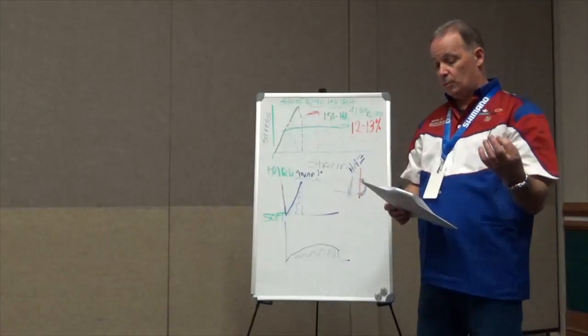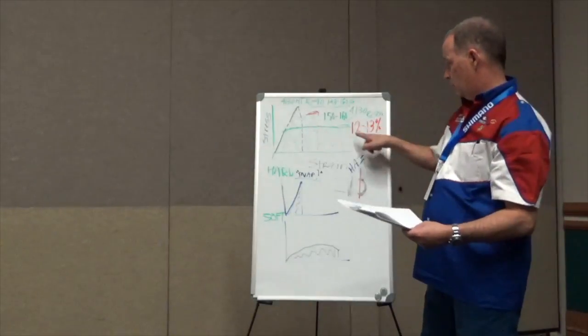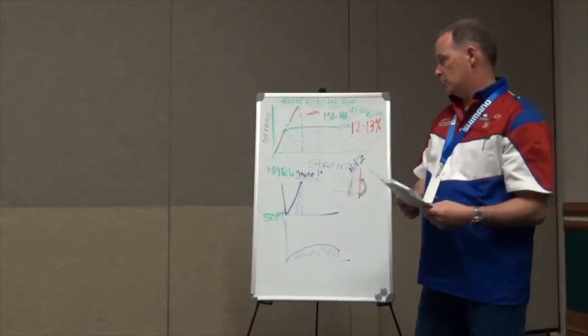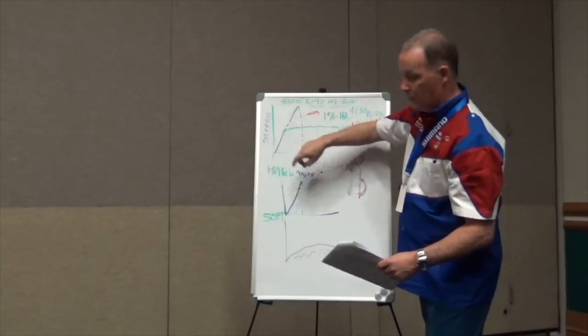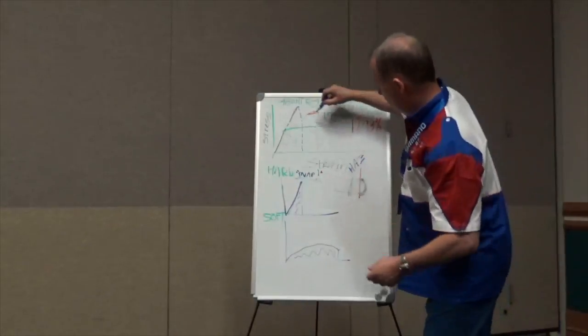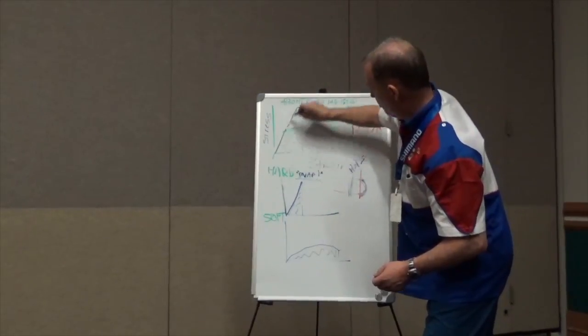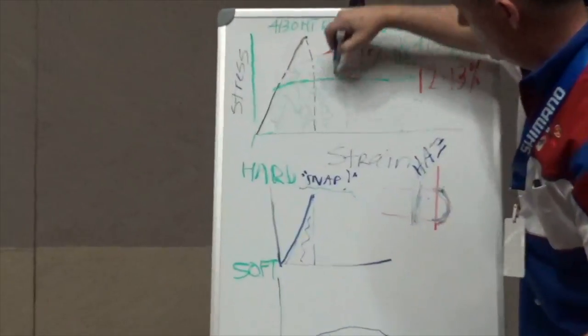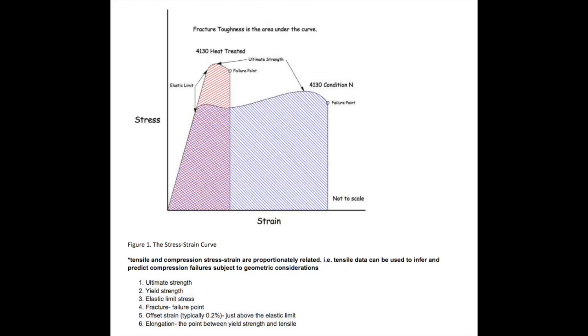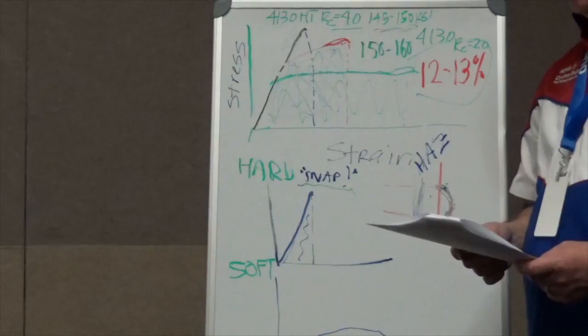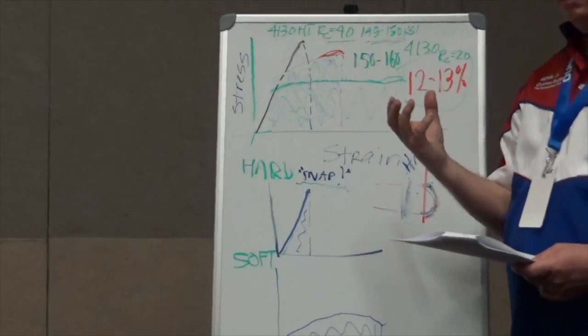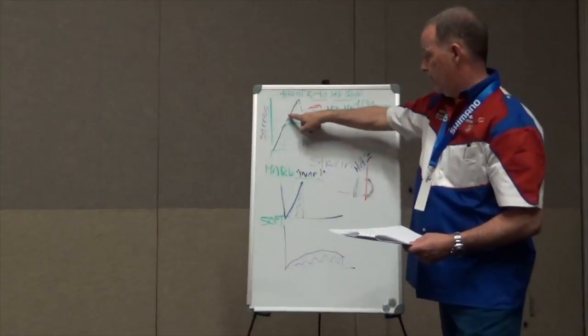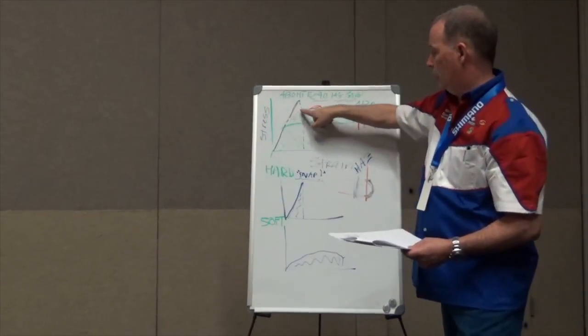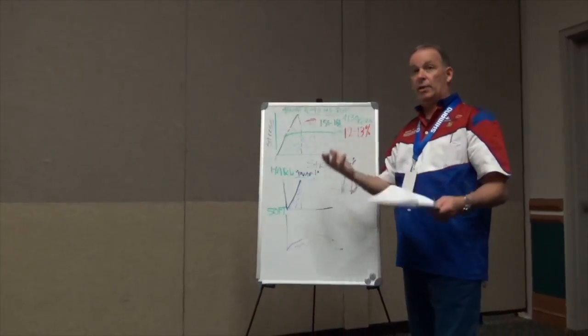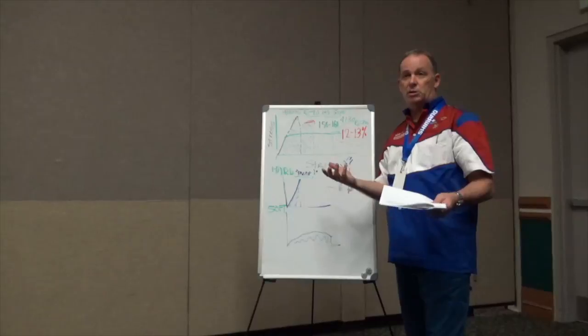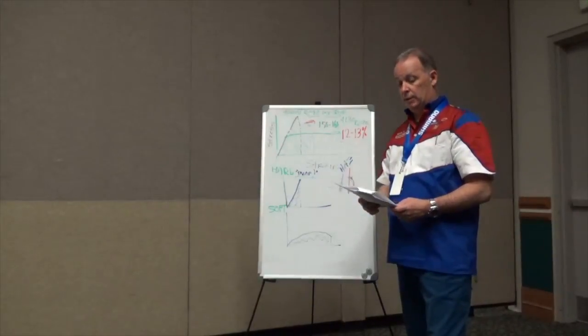Ductility and elongation matters. There are optimal numbers in elongation that give the best compromise, the best balance, so that you're getting the best strength. This. Not this, not this, this. This has the largest area. The ideal behavior is for a material to go as far as possible in its elastic area, and then have enough elongation to fail gracefully, so that you don't have a liability issue, and you also don't have a customer that's upset because his bike bent when it probably really shouldn't have.